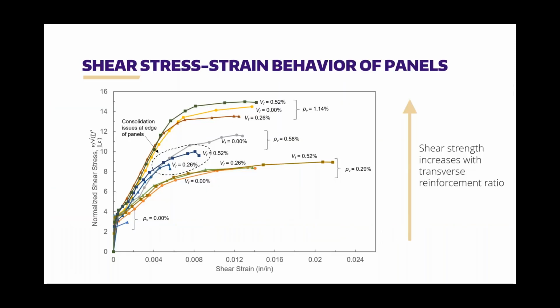So now I finally get to show you all of the data. So this is the normalized shear stress in terms of f'c. Sorry, the plot there had some weird characters happen. And the x-axis is the shear strain. And so you can see very clearly the 4 series in terms of the reinforcement ratio. And as expected, the shear strength increases with the transverse reinforcement ratio. That is sort of the obvious conclusion. You can see that the panels with no transverse reinforcement are sort of occluded by all of the other lines here, but their responses were quite similar.